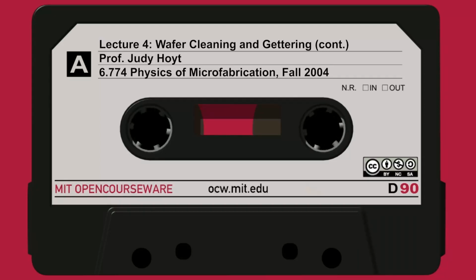So again, this is looking at it from the electrochemical point of view, and it's a little bit hand-waving, but it's consistent with the fact that when people do heavy N+ diffusion regions on the back of the wafer, like phosphorus, they can very effectively hold metals because of a higher solubility, just because of the electrochemistry involved.